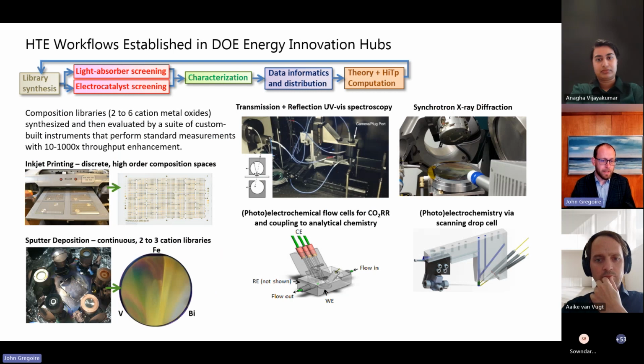The ones that we implemented in our years at Caltech are inkjet printing and sputter deposition. I'm going to talk about the inkjet printing technique today. We coupled these with a host of different property screening measurements, for both intrinsic properties and performance properties, particularly focusing on the electrochemistry field. We'll see one example of that in a second. The inkjet printing occurs by dissolving elemental precursors such as metal nitrates or metal chlorides into a solution that can be printed by modified Epson inkjet printers to print out large arrays of dots, where each one is programmed as a different color, which corresponds to a different composition, a different mixture of those elemental precursors.